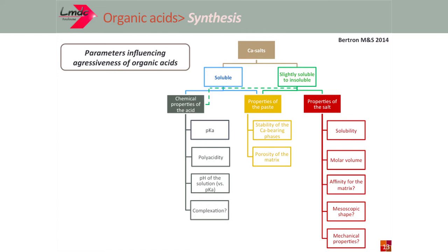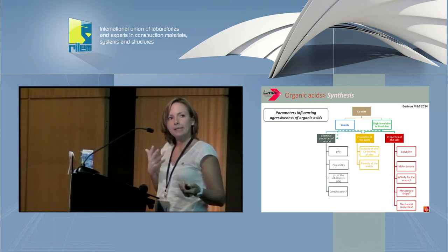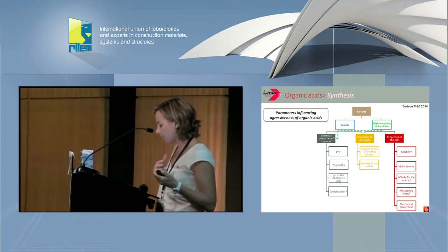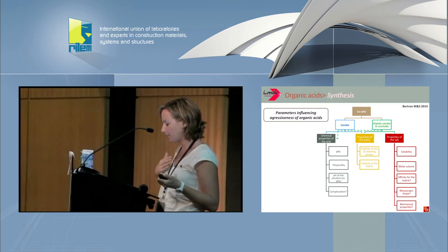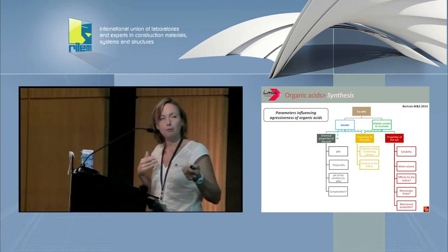But when the salt is slightly soluble to insoluble, the chemical properties of the acids are secondary parameters, and the properties of the salts are really important, such as the solubility or the molar volume. And some parameters seem to influence, such as the affinity of the matrix or the mesoscopic shape of the salt, but for the moment it's not really very well understood. And also the properties of the paste will influence the aggressiveness.